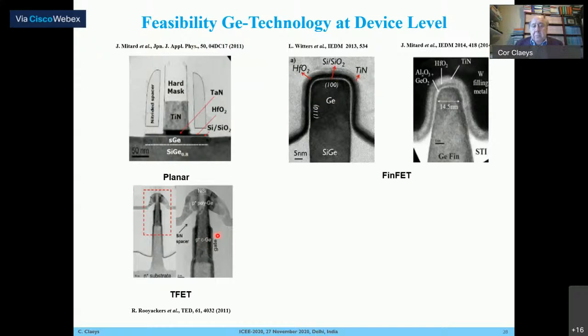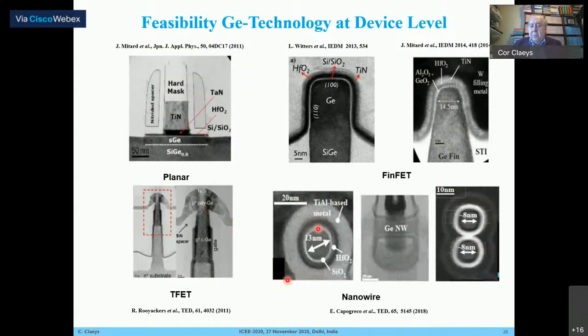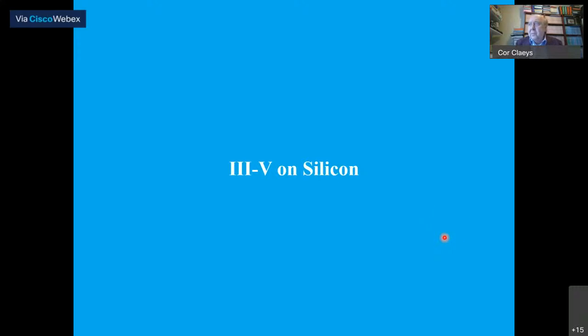That's why a very promising approach is to use only germanium in the source of your tunnel FET. And germanium has also been used to fabricate, as you can see here, nanowires, where we have germanium nanowires with a thin silicon layer on top of it before depositing the high-k dielectric. So we can say that very good, even promising performance of germanium devices has been reported, especially for P-type devices. However, if you want to have high-performing N-type devices, then you better switch over to III-V materials.